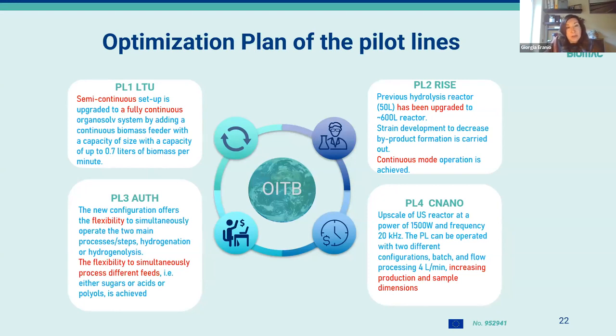Pilot line 3, by AUTH, managed with a new configuration to achieve higher flexibility and simultaneously operate the 2 main processes, the hydrogenation and hydrogenolysis. Then they managed to simultaneously process different feeds, either sugar or acid or polyols, according to the needs. Then pilot line 4, by CNano, managed to upscale the ultrasonicator reactor, enhancing the power and the frequency. And then they managed to operate in 2 different modes, batch and continuous mode, with a velocity up to 4 liters per minute, thus increasing the production capacity and at the same time the sample dimensions.